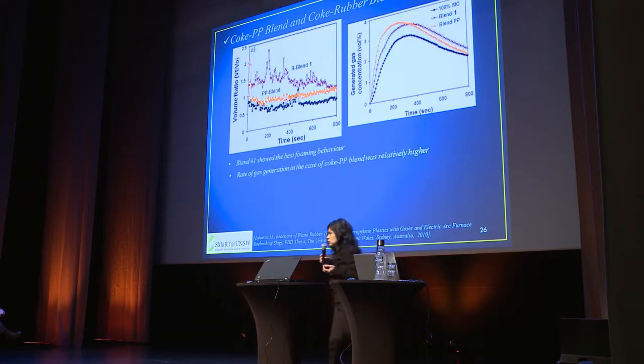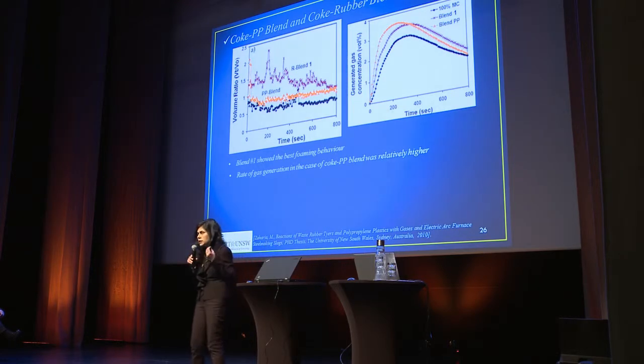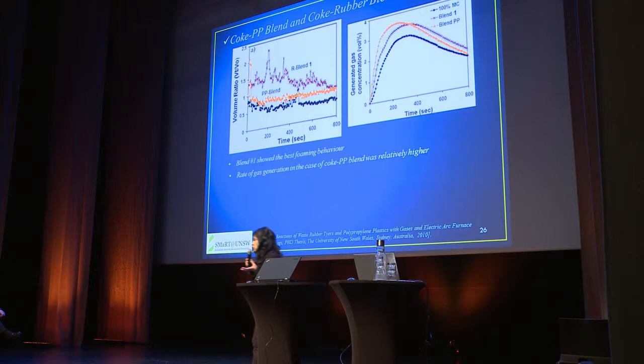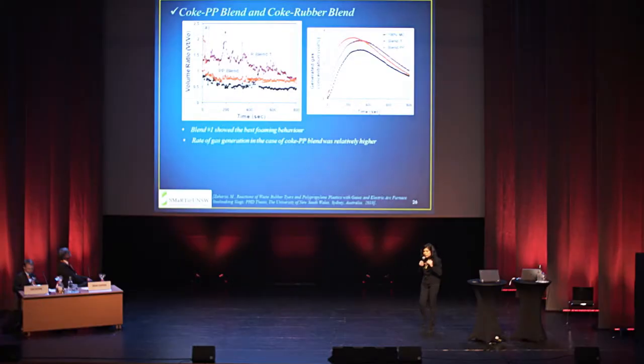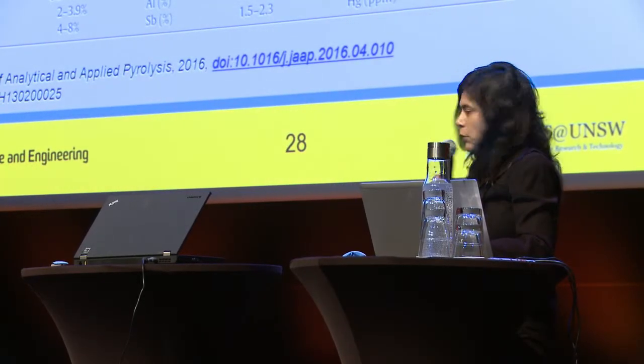You can see we introduced polypropylene in the blend and compared that to rubber. Now the polypropylene blend still shows better performance compared to the black line, which is metallurgical coke, but certainly you can see that polypropylene doesn't perform as well as the rubber blend does. And again, that is attributed to the fact that you've got far too much gas coming out from the system far too quickly. So if it's not doing such a good job with respect to slag forming, well, let's look at what else we can do with it.